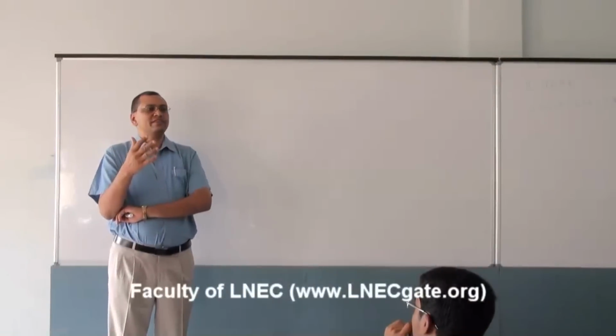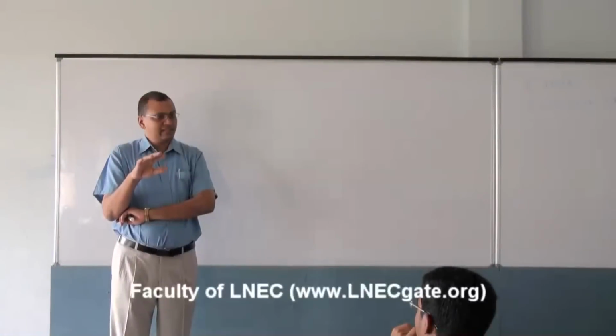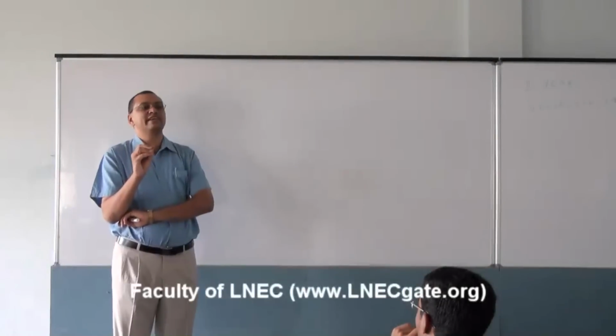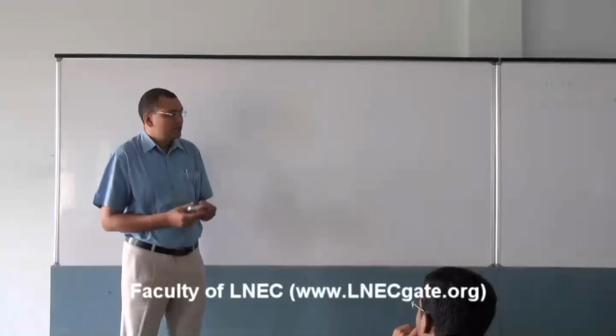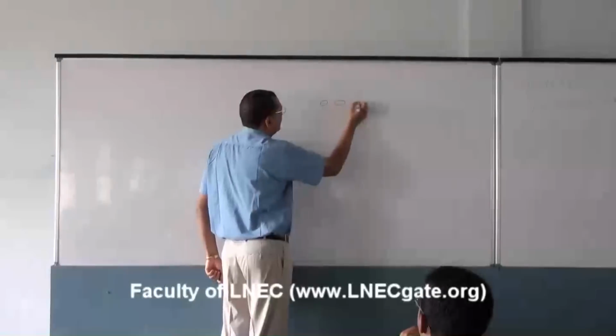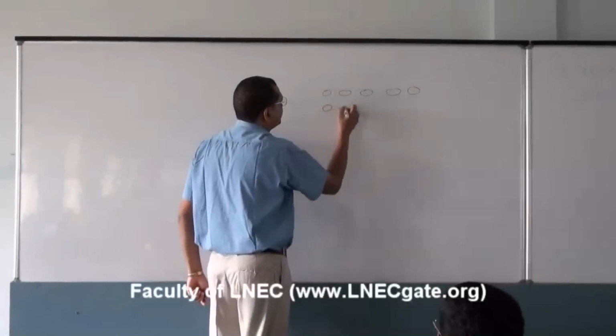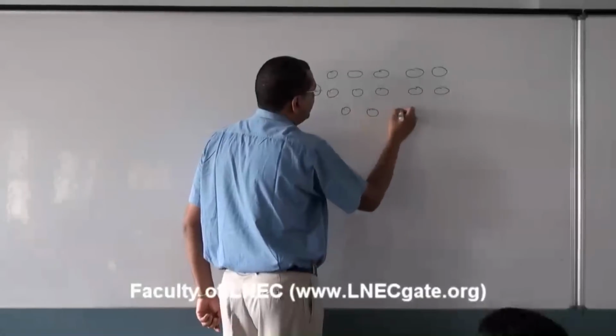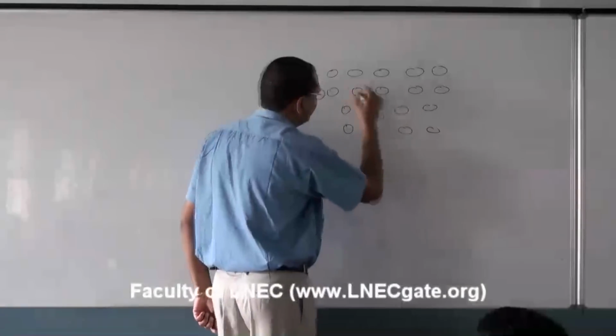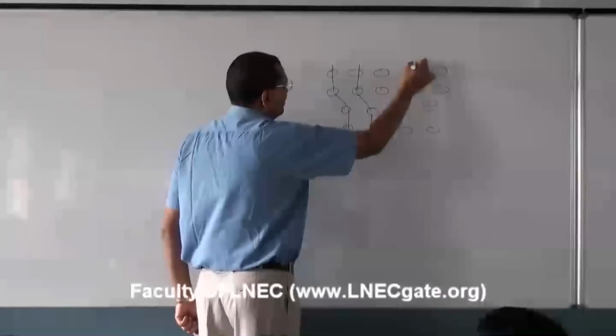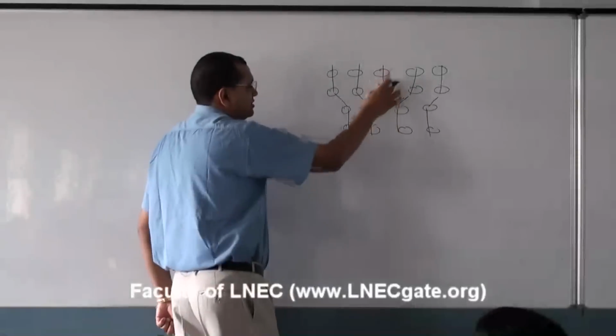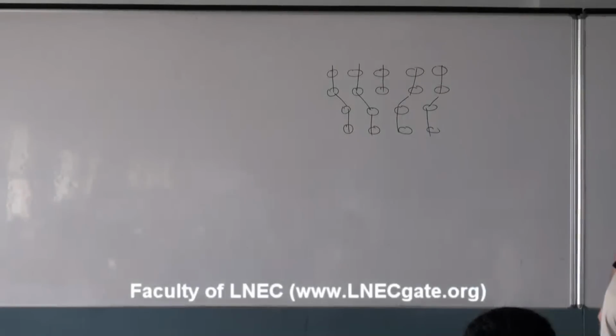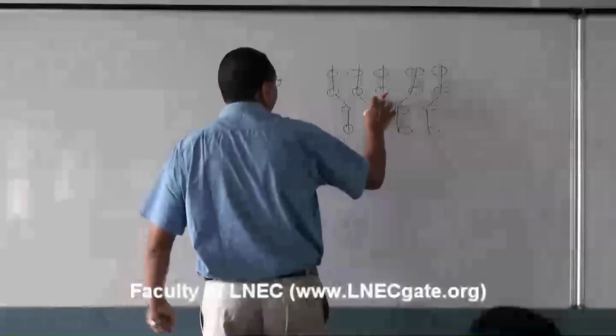So, as we discussed, millions of dislocations will be there within the material, and when we apply load on the material in any direction, dislocations within the grain present in that direction start moving. So as just now we have seen that there are dislocations in every material. So let us say there is an edge dislocation here. That is an edge dislocation, and this is an extra half plane, and here is the dislocation site.